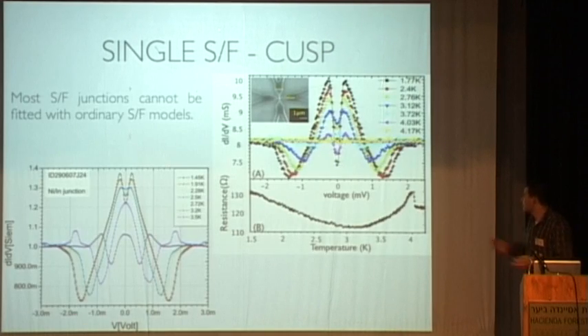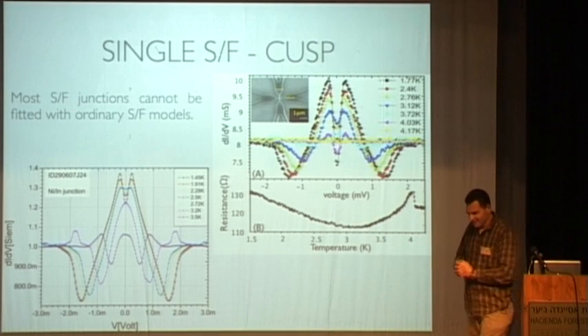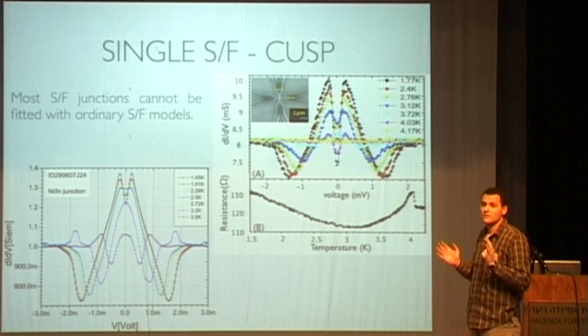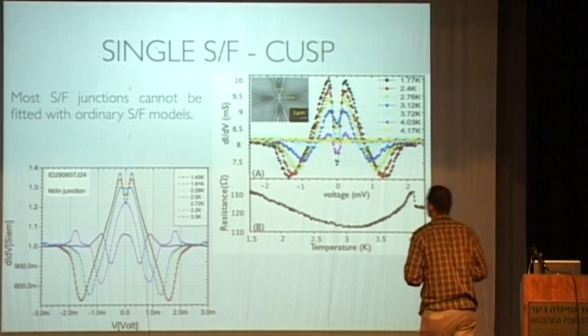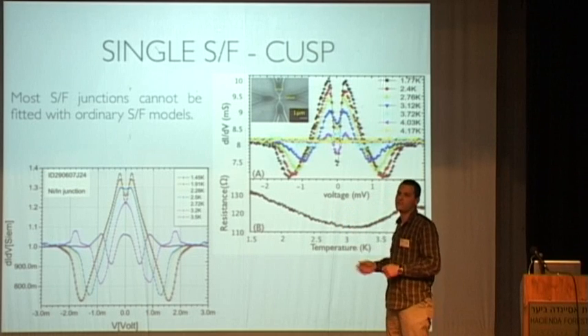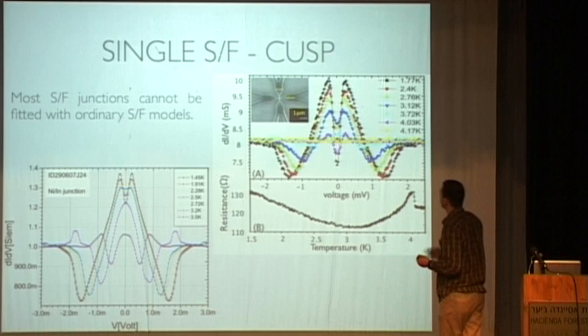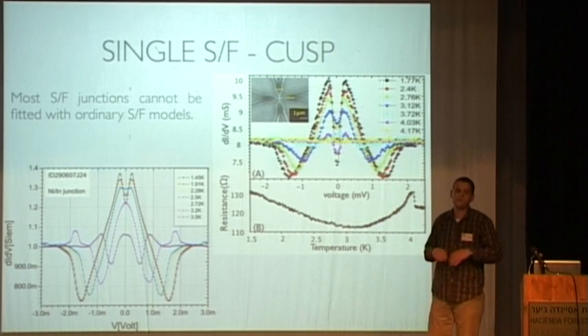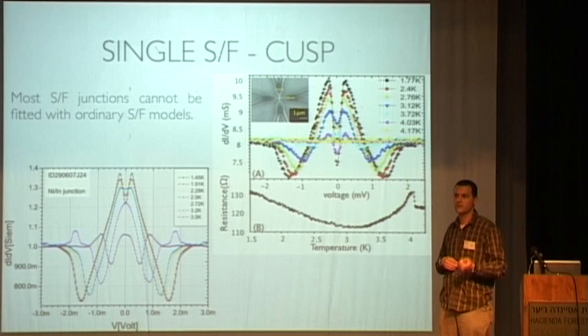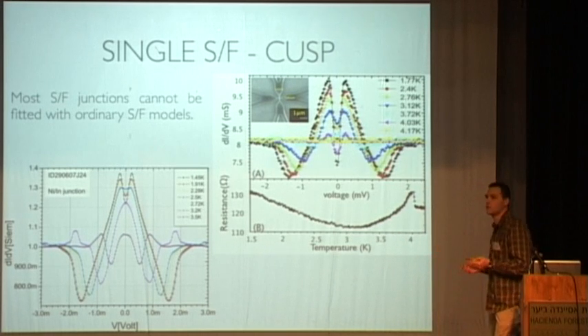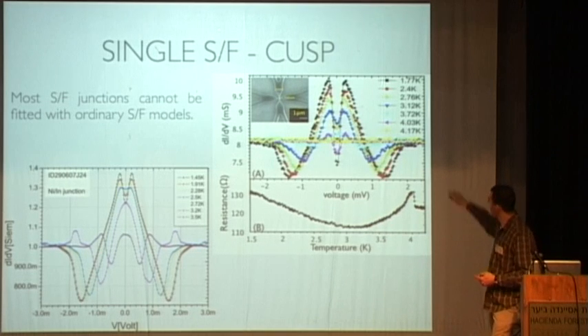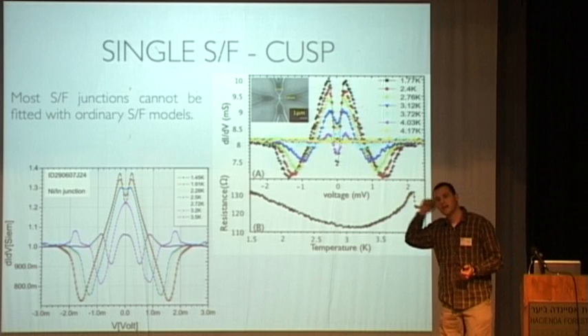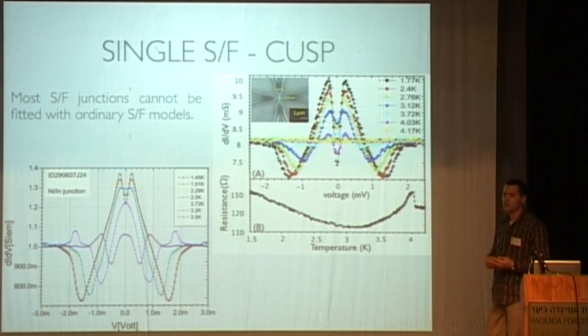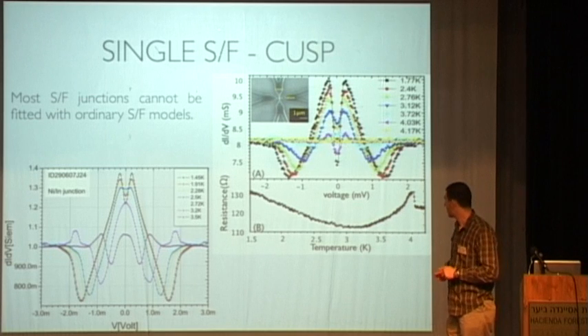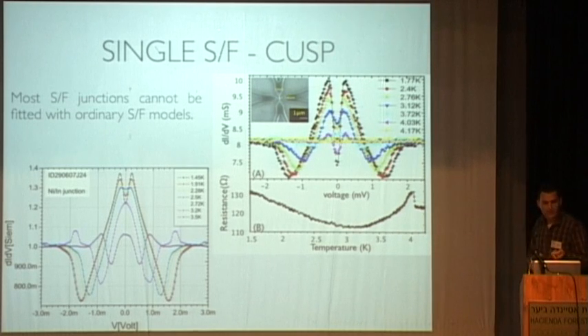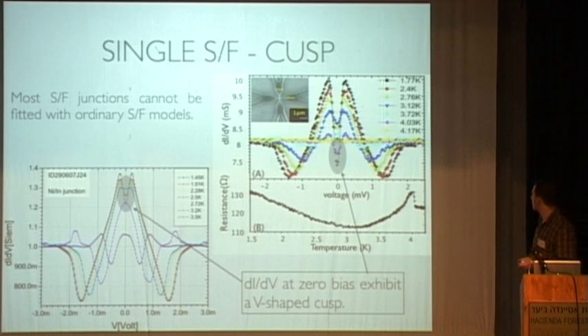Now, sorry for the scary data, but this is a typical conductance measurement, in which you see the conductance as a function of the energy, of the voltage of the electrons. And at high energies, you see that the conductance is flat. You destroy superconductivity at high electron energies, and you go back to the normal conductance. And at low energies, you see some kind of a peak, which is the Andreev reflection peak, or the enhancement in the conductance due to the double electron that you transferred. But what is interesting in our contacts is the V-shape in the middle.